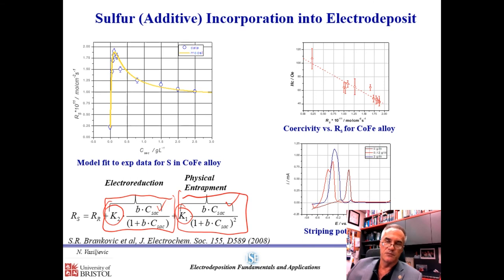So if you have some process that you want to do and you use specific additives at specific conditions, and you want to study a little bit more, the best idea is to find some tracer element in your additive, like for example sulfur in saccharin, and follow the content of this element in your deposit as a function of the concentration of your additive in the plating solution. And what is interesting is that you're getting this kind of behavior in general. It can vary, maybe it can look like this, it can look like that, depending on the ratio between K1 and K2, or basically these electroreduction and physical entrapment constants.